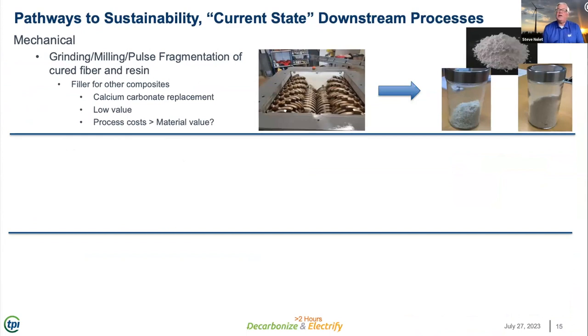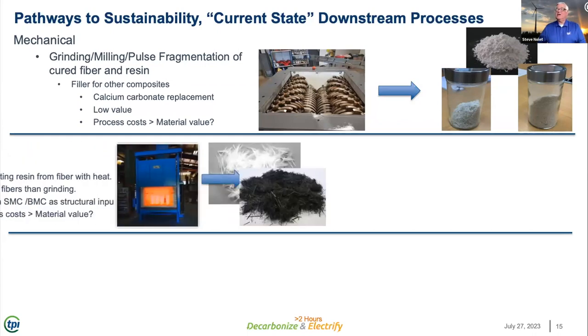Once we're in a process plant, what can we do? What are our pathways for successful downstream processing? Well, we generally break this down into three operations, looking at mechanical systems that might be grinding or milling or some form of other energy pulse fragmentation to separate cured resin from fiber. That generally is creating fairly low value particulate, whether it's staples of fiber or powders or granular materials used for aggregate reinforcement. Process costs tend to be greater than the material value itself.